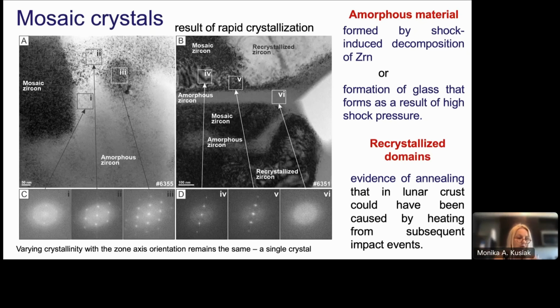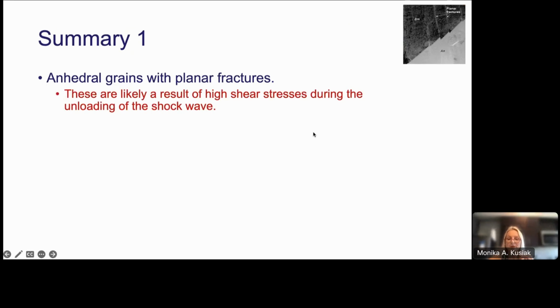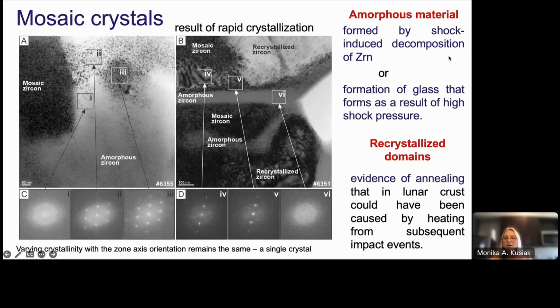And then we go to the second and third, more slightly crystalline material. Here what we notice are slightly sharper spots and less diffuse scattering intensity from amorphous material, which indicates crystallization of nanocrystals of zircon. So here is a very nice example of this process of crystallization of nanocrystals of zircon inside a really big single crystal. So amorphous material formed by shock-induced decomposition, or formation of glass as a result of high shock pressure, and recrystallized domains are evidence of annealing that in the lunar crust could have been caused by heating from subsequent impact events.